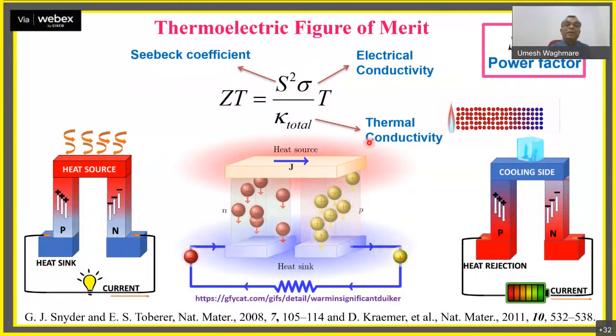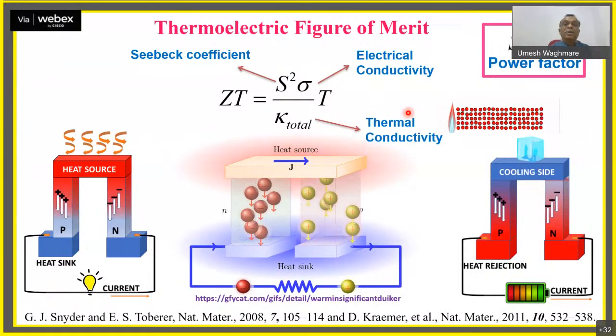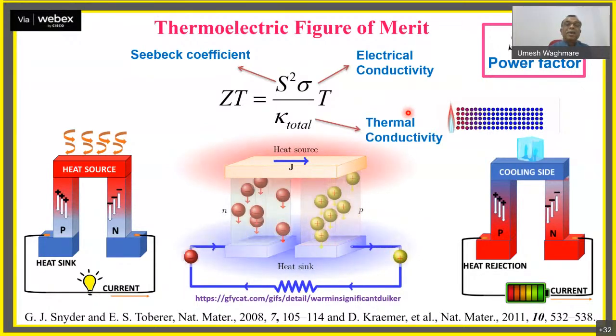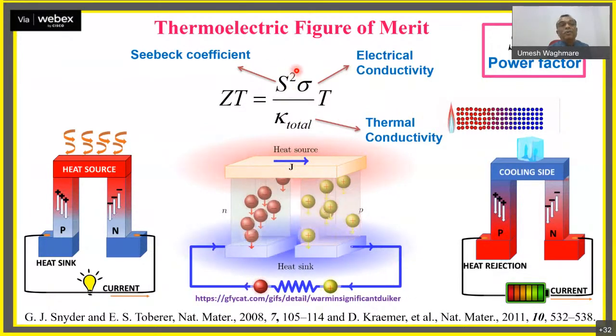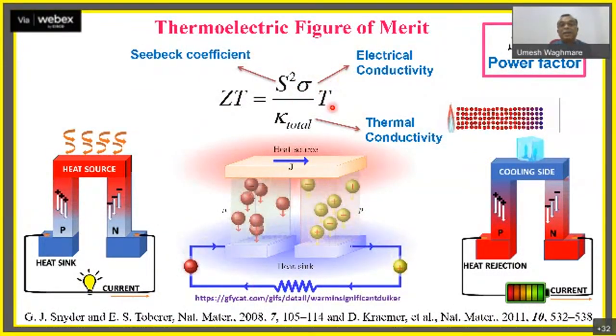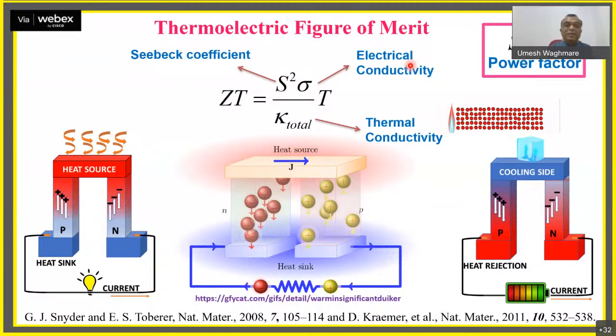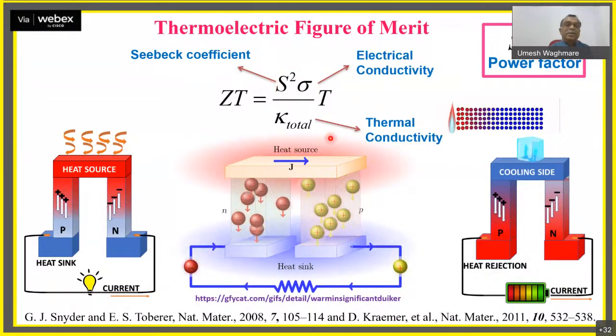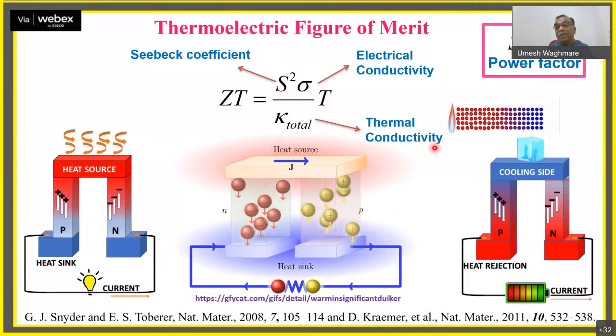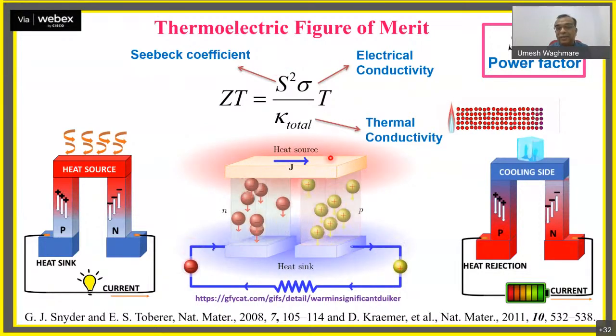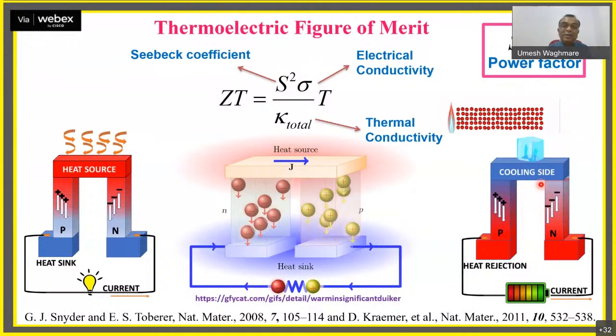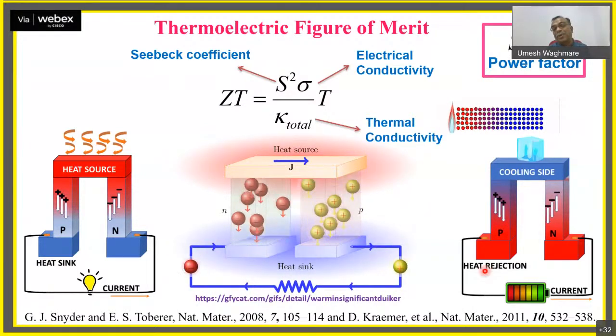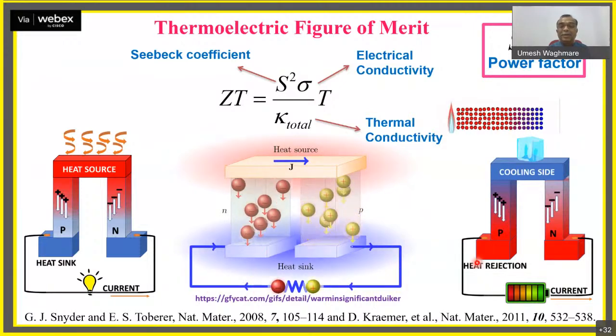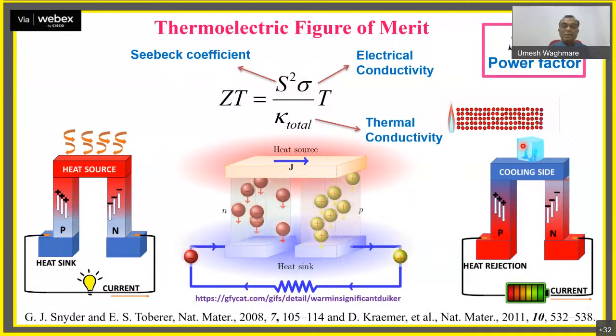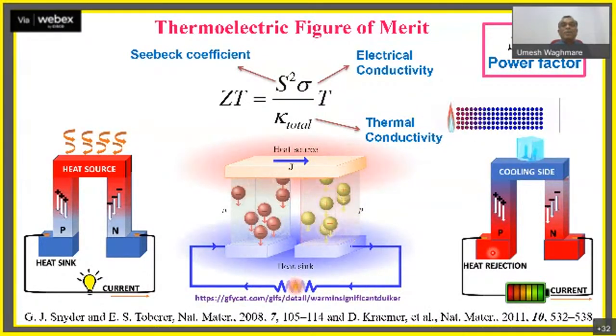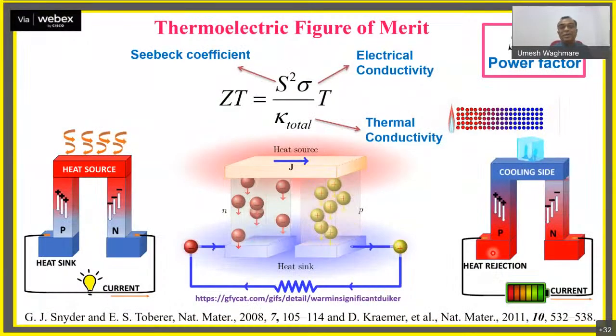So for an efficient thermoelectric, you need a very low thermal conductivity, ultra low thermal conductivity, like a glass. You need a high Seebeck coefficient like a semiconductor and high electrical conductivity like nickel. So a single material should behave like a good metal, good semiconductor, and good glass in different domains of properties. If you can develop a material like this, you can also use it to refrigerate things. So in the villages where you have chulhas, you can also have a fridge attached to it, which will be using the heat generated by the chulhas and cooling by rejection of heat. So it's a very appealing material which can enable technologies.